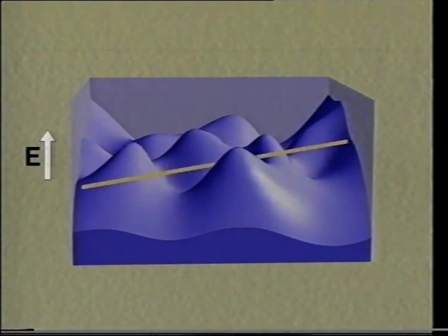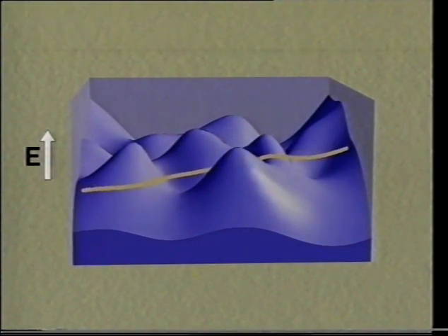First, consider a straight dislocation draped across the landscape. The force acting on any part of it, such as here, depends on the slope of the hill measured at right angles to the dislocation. As you can see, in some places the force acts to the left, and in other places it acts to the right. In a random jungle, the forces on a straight dislocation would indeed cancel out. But why should the dislocation remain straight? A dislocation is flexible, so it can reduce its potential energy by moving downhill towards the bottom of the valleys.